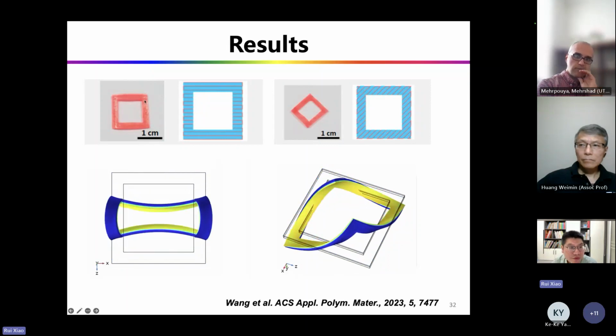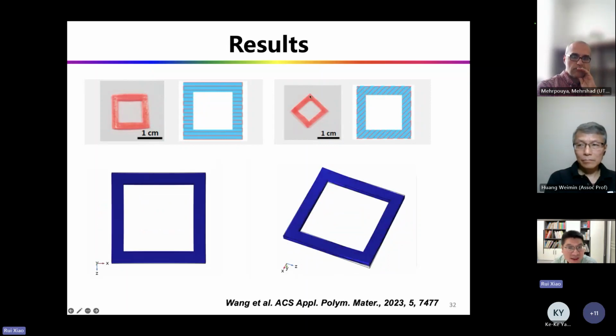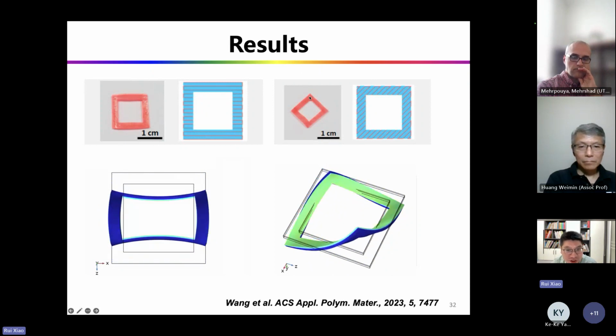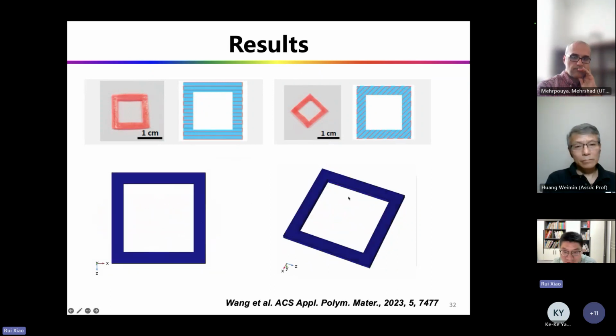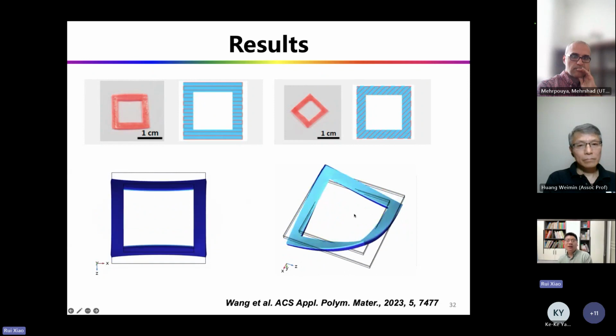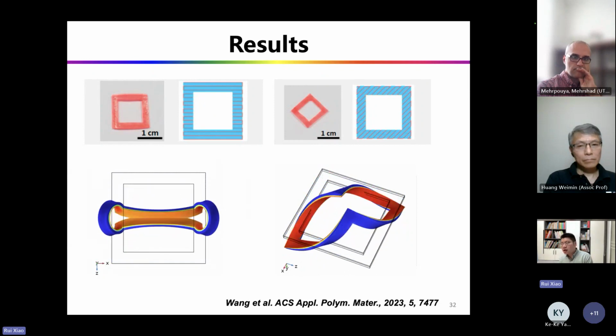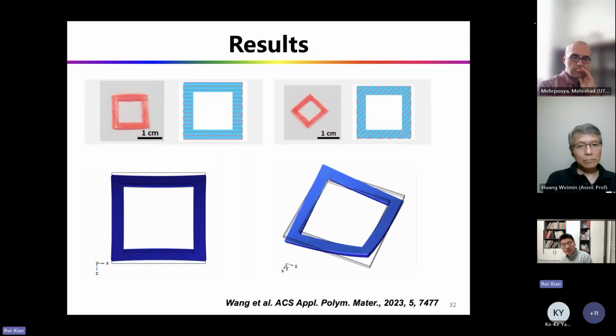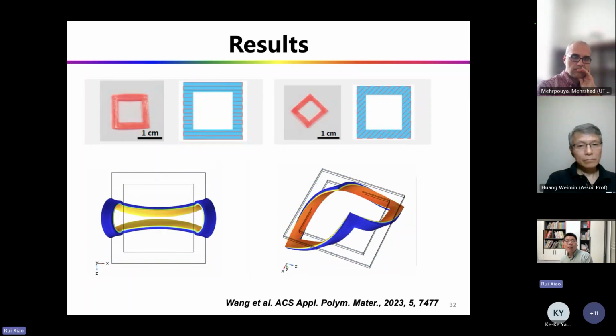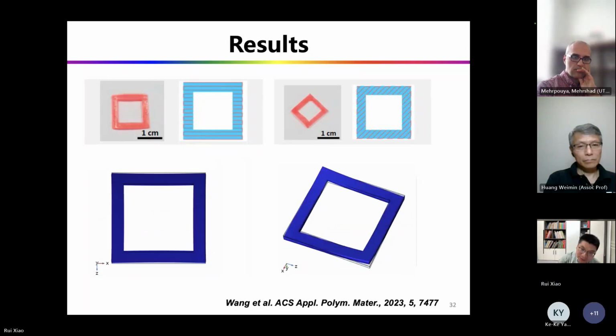From the shape, you can really tell the difference. The two look exactly the same, but if you change the temperature, they have very different shape changes. That is, by controlling the orientation of the mesogens, you can create very complex structures.